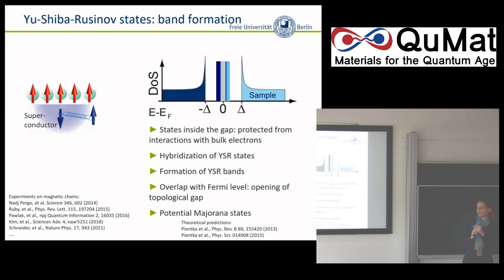And then you would be in the regime of topological superconductivity, and this has been discussed a lot, that then you should be able, if you were to construct, for instance, a magnetic chain on the superconductor, which obeys these particular energy level alignments, then you should also get Majorana states at the very chain ends. Okay, so well, this is the rough background.